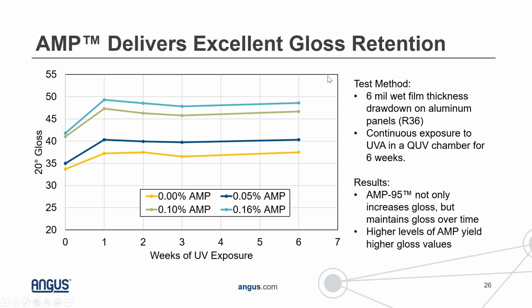Our control sample here is shown in yellow, and this was the 0% AMP. That has the lowest gloss values, but the gloss retention is fairly consistent over time. There's an increase after the first week of UV exposure, but it maintains itself over the subsequent 6 weeks. But what we see is with increasing amounts of AMP, we really see a strong increase in the gloss. Again, we still see an increase after that first week of UV exposure, but we also see that it's stable over time. So AMP can not only increase the gloss, but it will make sure that it's stable.